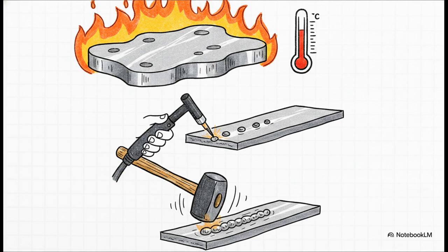You've got to use really small weld beads to keep heat input low. You should be mechanically peening the weld between passes to relieve that stress. Keep your arc time minimized, and always direct your arc into the weld pool, not directly into the base metal. You're trying to gently coax this metal together, not blast a hole through it.